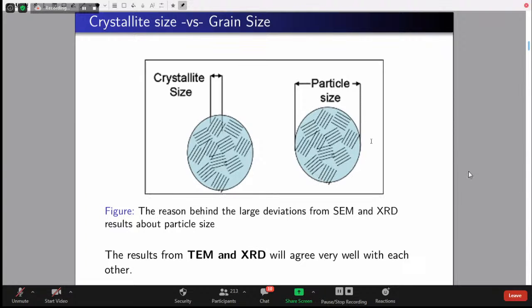And this is the one. So this can contain several crystallites which are oriented in several different orientations. When X-ray is going to measure them, it will measure only this part. So now you can figure out why from SEM we will have larger particle size, and when it comes to X-ray diffraction, why it is very small. Right. So in X-ray diffraction, they define them as coherently scattering domains.